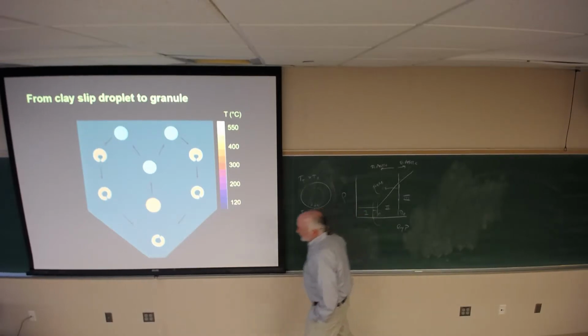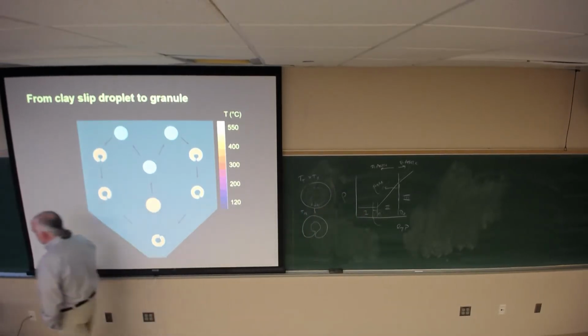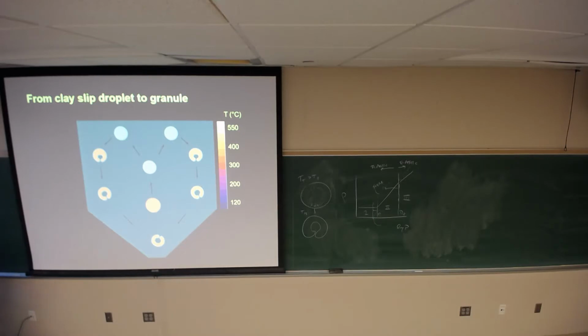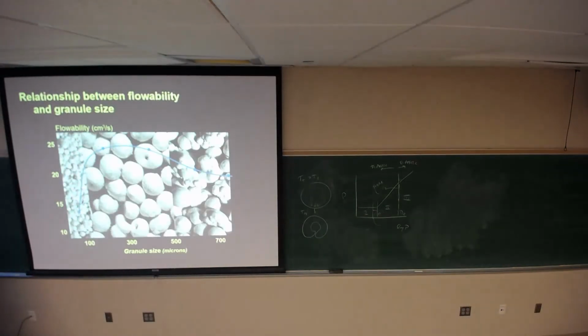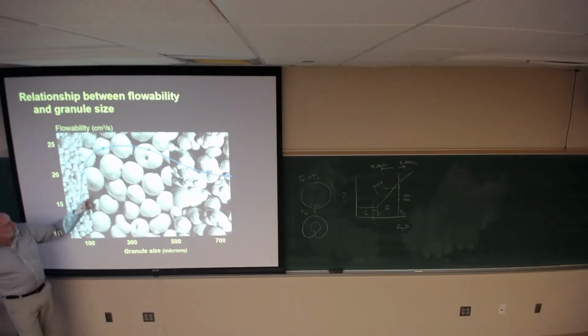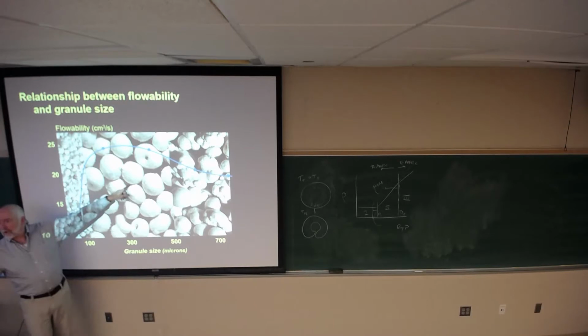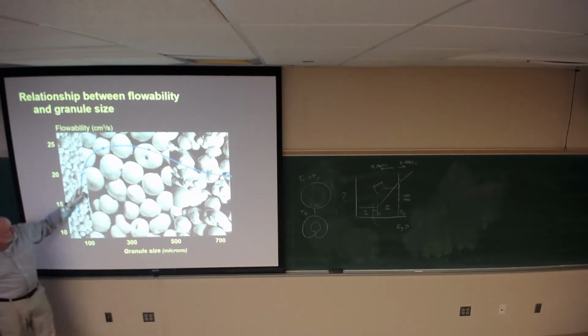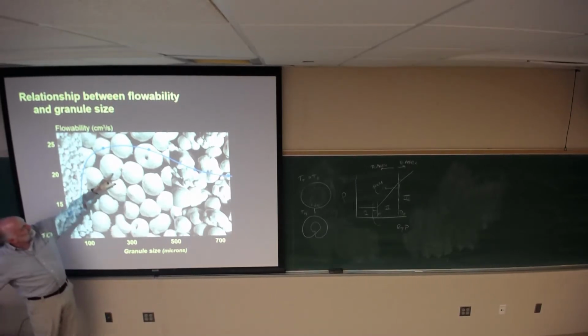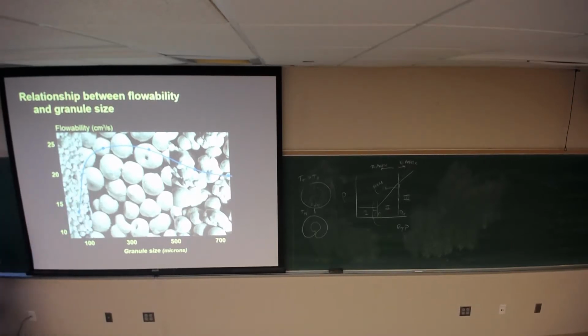It's not spinning, so you end up with a non-uniform temperature gradient, or you end up with a uniform temperature gradient from top to bottom. And so what you get here is, if you look at these images, you get that, or you get this. That one looks perfect, but I suspect if we flip it over, it's got a hole in it. So the problem is that when you look at these, you see a percentage of these. You know, in the field of view, we have 1, 2, 3, potentially 4 that have a hole in the middle.